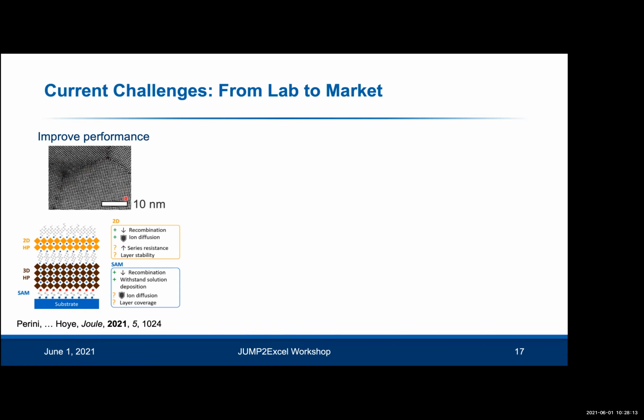Another thing that needs to be done is to further develop better strategies to passivate surfaces and interfaces. There's already been a lot of work on using long chain ligands to passivate the top surface, but there also needs to be work done to passivate the bottom surface, which is more challenging because this is a solution-based technology. So you can wash away the passivation layer. And an emerging concept is to use self-assembled monolayers, which could anchor themselves to the substrate.